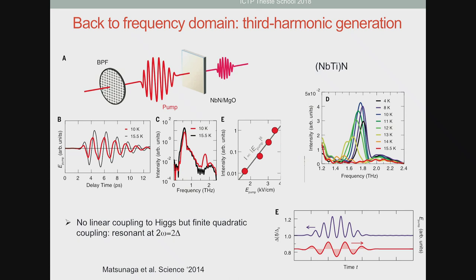And what you see, the key curve I think is here, is that you have the fundamental located right below 1 terahertz. And when you cool down below TC, there is indeed a harmonic of this fundamental here at 3 omega that is only seen below 2 delta. And the intensity of these harmonics follows the sixth power of the pump, which is also what is expected for a third order nonlinearity.